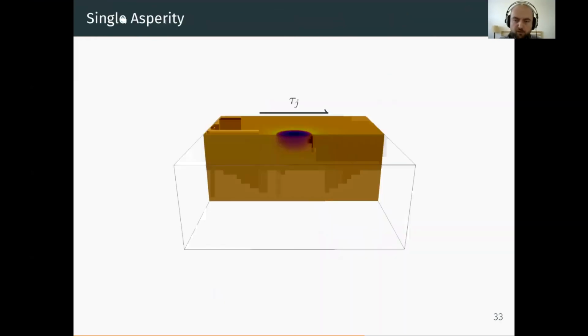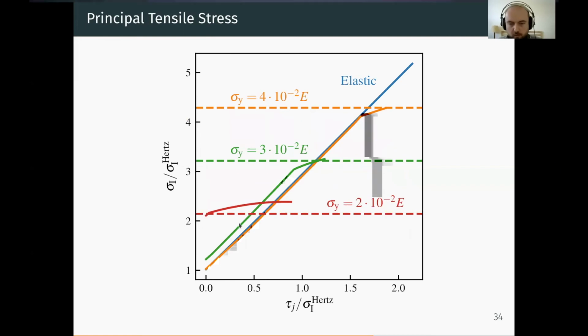To rationalize a bit those observations, I did simulations of a single asperity where I push a spherical indenter onto an elastoplastic half space. I shear it with tau j, and I compute the principal tensile stresses at the surface. And what I get is this curve of sigma 1 as a function of tau j. In blue, you have the elastic behavior, which is essentially unbounded. And as you increase tau j, you increase in proportion sigma 1. But if you have plasticity, you have something that is very similar to hardness. As you increase tau j, at some point, you deviate from the linear behavior, and you have a nonlinear state, where as you increase tau j, you don't increase as much the tensile stresses in the system.